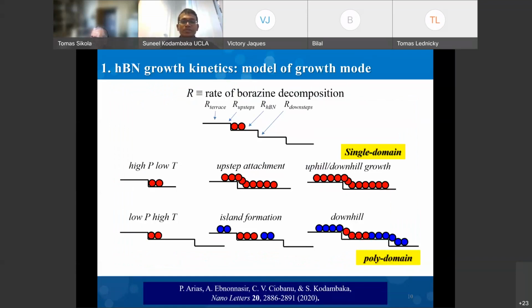And so based on these observations, we've formulated and explained how these layers grow. In both cases, you end up with a carpet. But in one case, under high fluxes of borazine and lower temperatures, you are likely to get a single domain boron nitride, whereas at the other extreme, you end up with polydomain boron nitride. Okay? And so there are interesting details regarding how two-dimensional layers grow on these surfaces.